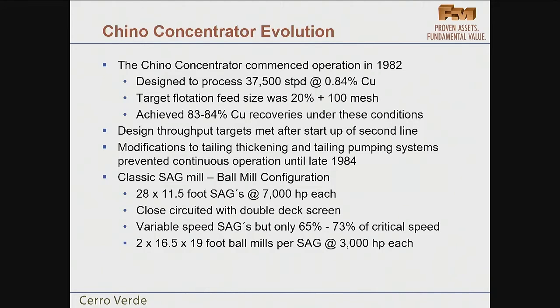The Chino concentrator started at 37,500 tons a day in 1982. Head grades were much higher in that era, 0.84%. Targeting a 20% plus 100 mesh flotation feed size, they were able to get 83-84% copper recoveries.